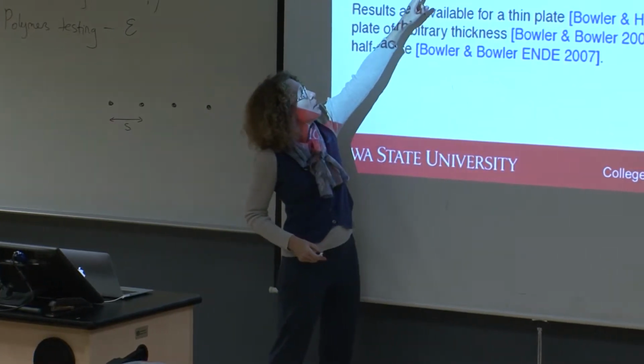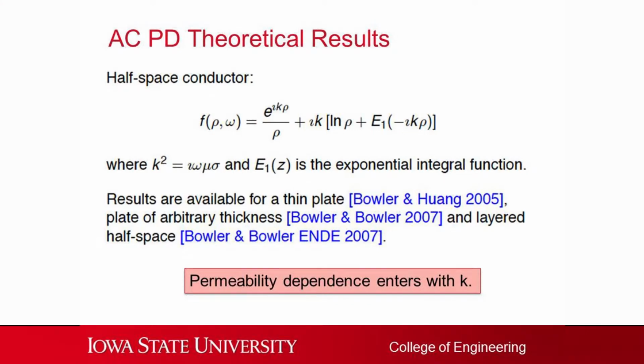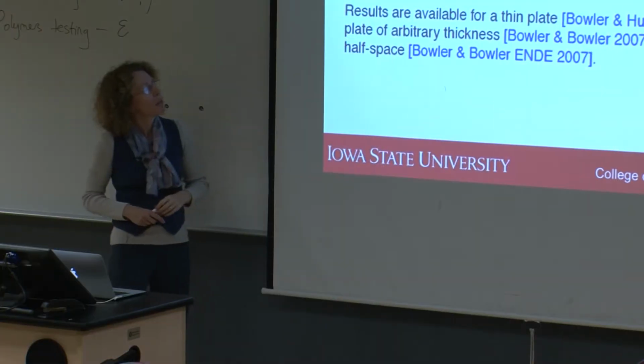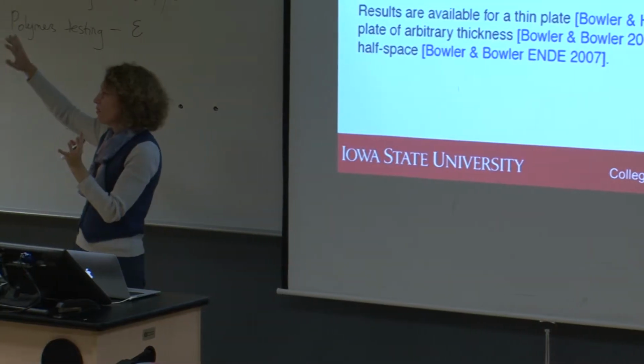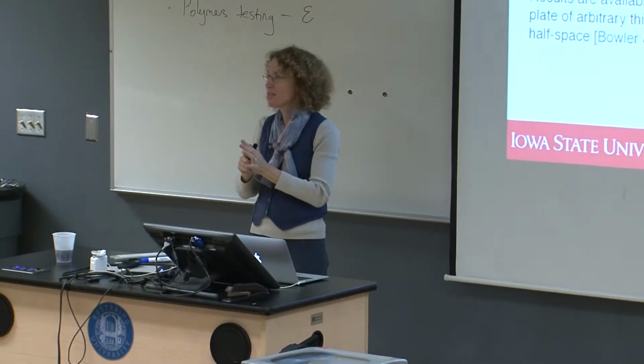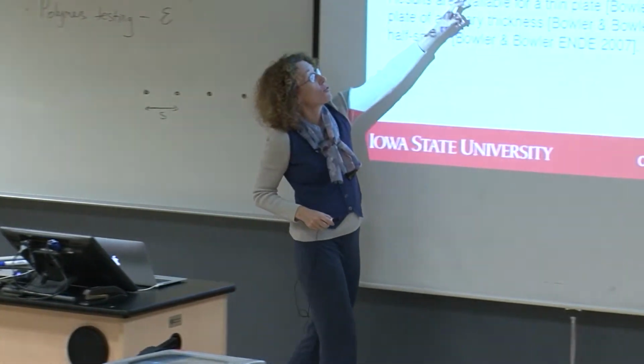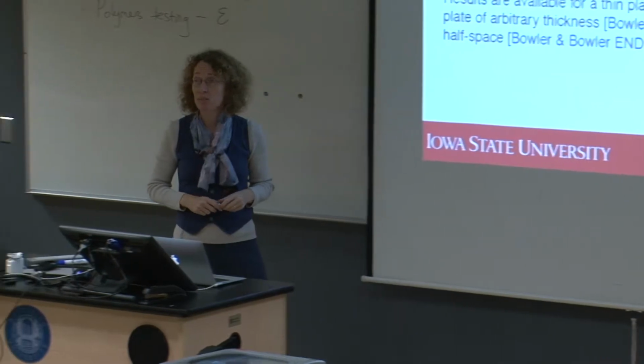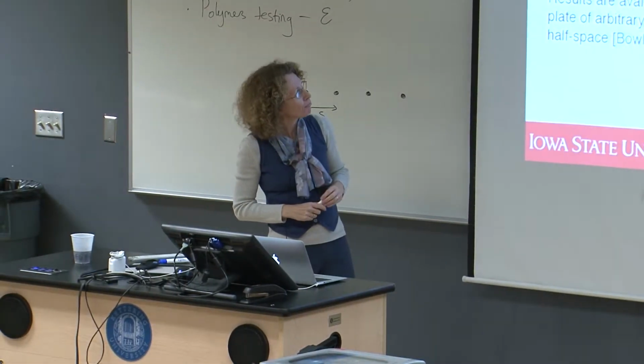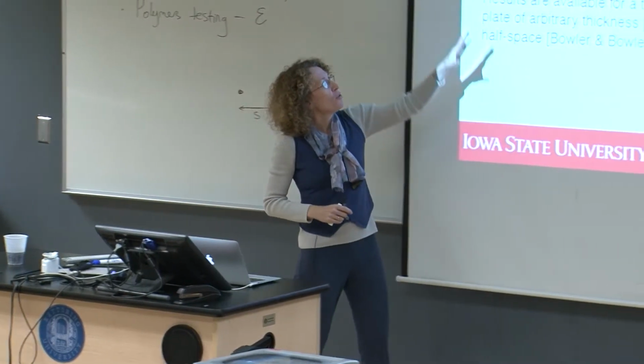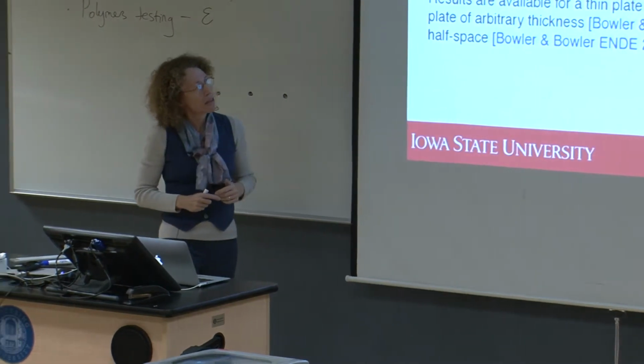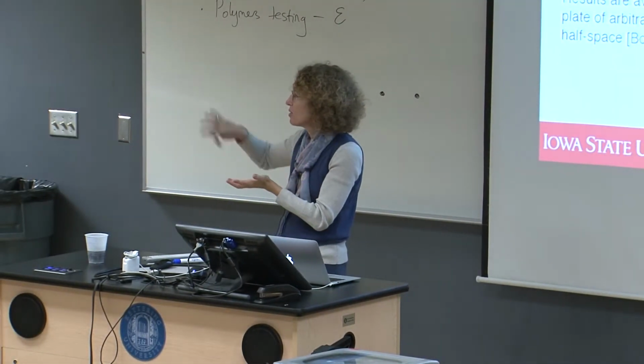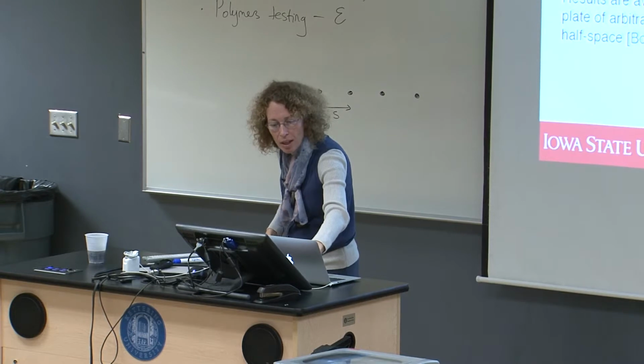So we have the imaginary unit here, then we have the angular frequency, we have the permeability of the material, and we have its conductivity as well. And so that's why as you go up to higher frequency and that curve changes, we can actually extract permeability information about the material as well. Okay, so you can have a function like this, and that's how we could get that nice fit between experiment and theory.